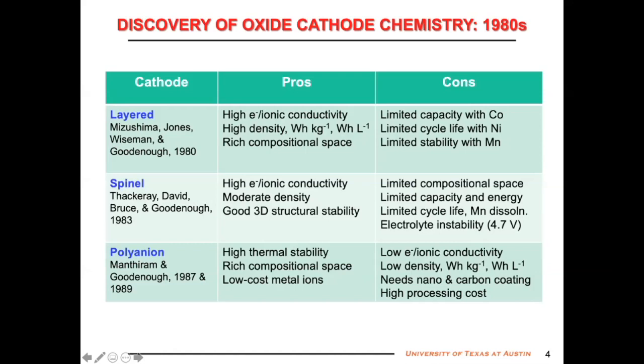And each one of them has its advantages and disadvantages. I have listed some of them here, but I will point out the major advantages. The layered oxides have high electronic and ionic conductivity. They are also highly dense, so we can get much higher energy density with the layered oxides compared to the others. But there are limitations. With cobalt, you cannot charge more than 50%. With nickel, there are cyclability issues. With manganese, stability issues. With spinels, again, we get reasonably good electronic and ionic conductivity. They have good structural stability, but there are limitations on the cyclability.